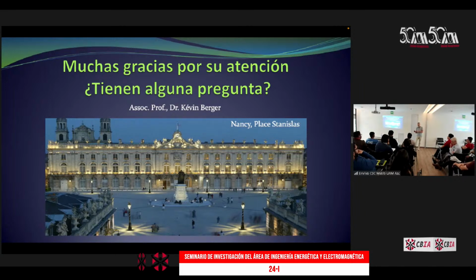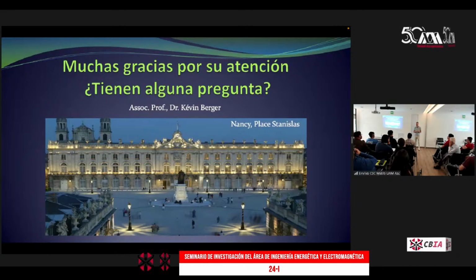But on the side of the DC magnets, there are what we call hybrid magnets, but the field is in the range of 45, 46 Tesla. So the record will be at Tallahassee at the moment, I suppose, and it's a hybrid superconducting magnet. Since the superconductors used in this kind of application have some limits in terms of magnetic field, they use a combination of a huge magnet made with copper to produce a very big magnetic field, and there is an insert with superconducting cable to reach another range of magnetic field, decreasing the size of the magnet. At the moment, the record is 45, 46.